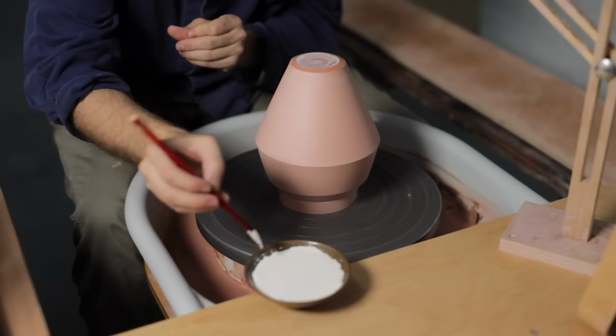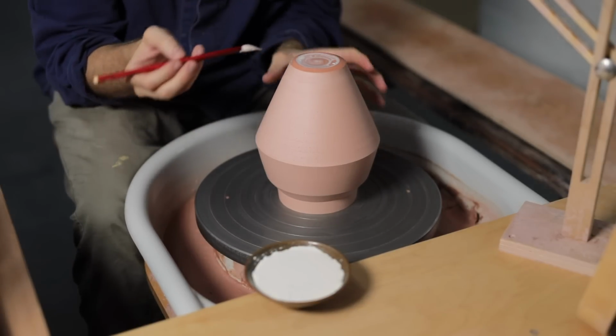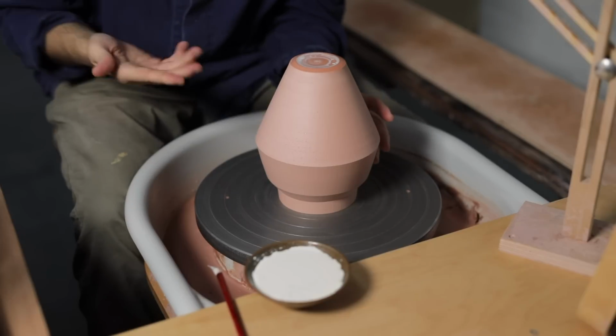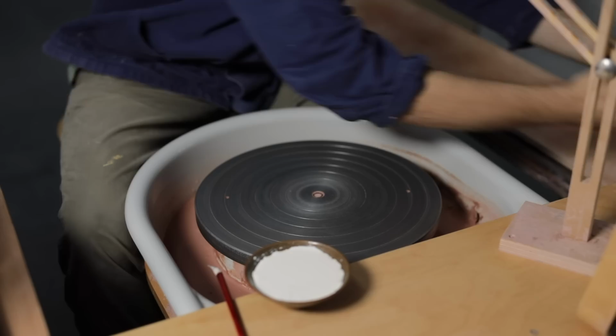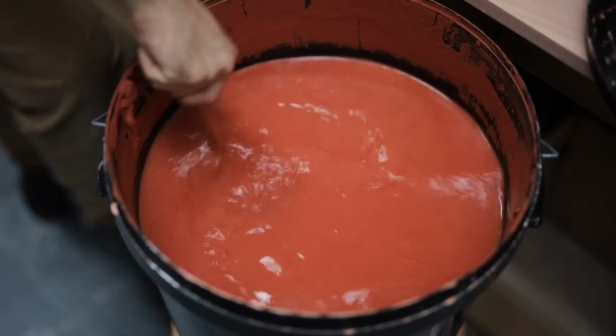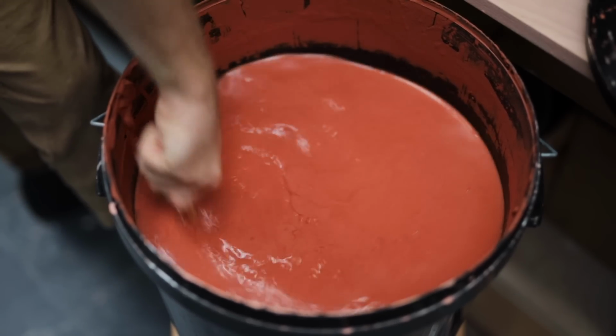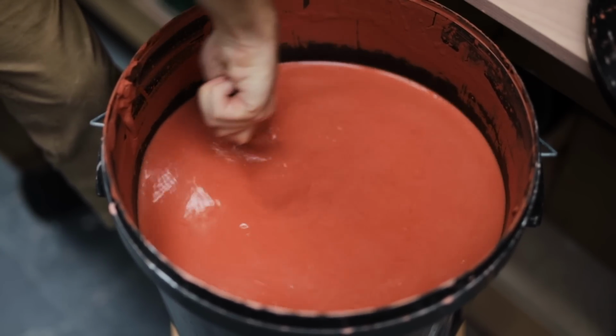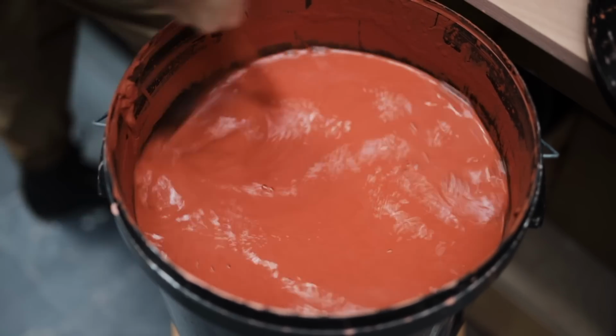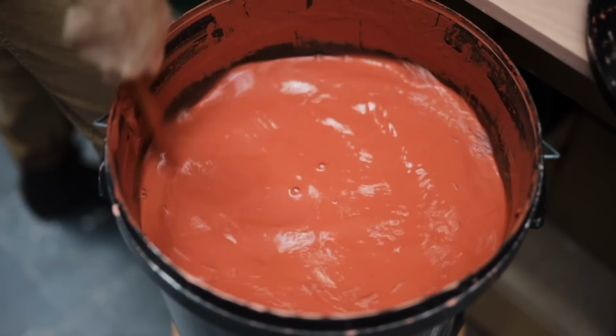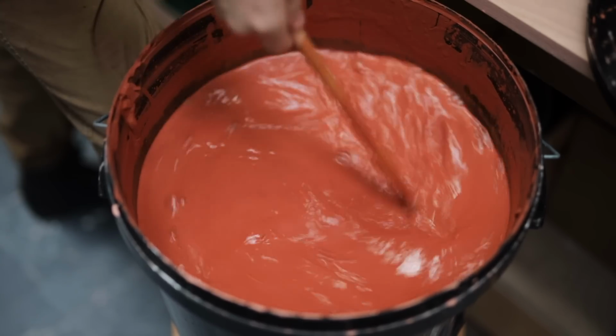This won't act like a perfect seal, and some small specks of glaze will settle on the wax, but it makes the process of tidying up each pot after it's been glazed much easier. I'll be coating this pot with a feldspathic crackle glaze with a colorant of 2% red iron oxide, which, whilst red here, will fire to a deep dark green.